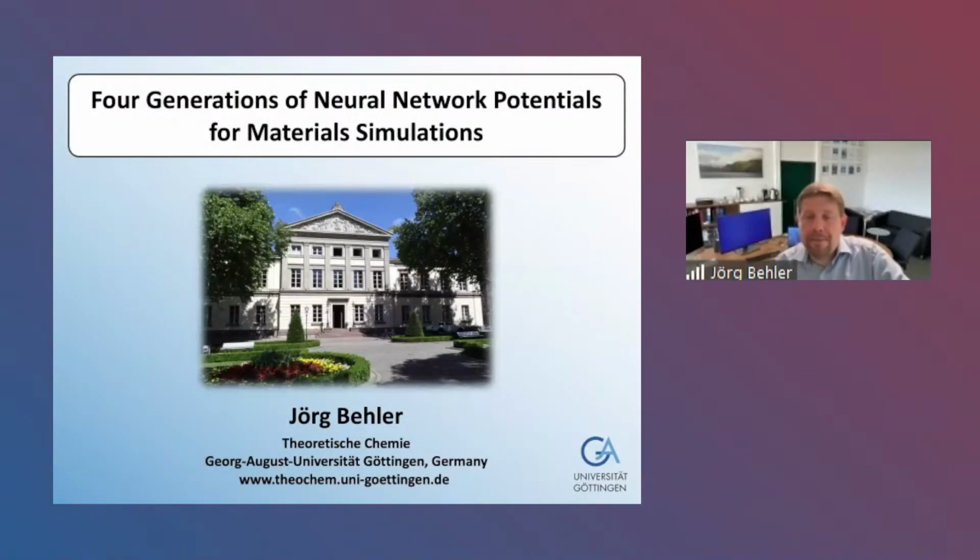Yes, that's a very good point. This is, of course, the critical aspect, because the main motivation was to have an accurate representation of the potential energy surface. Well, I'm always thinking in eV, that's just because I have a physics background, so the typical goal is to reach an accuracy for total energies, with respect to the reference electronic structure method, of about 1 milli-electron volt per atom. So why per atom? Because of course we need to compare the accuracy in a size-consistent way for different systems. If we double the system size, twice the same system, of course, we also have double the error. But most important in chemistry and materials science are always energy differences, and here errors cancel, like they do also in DFT.